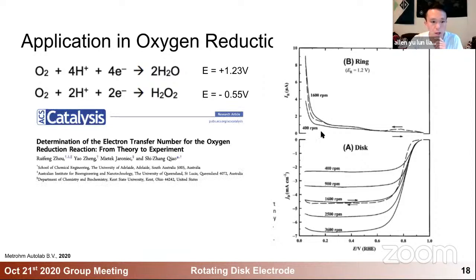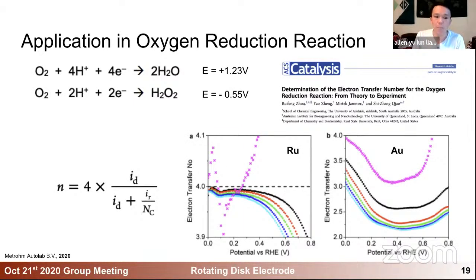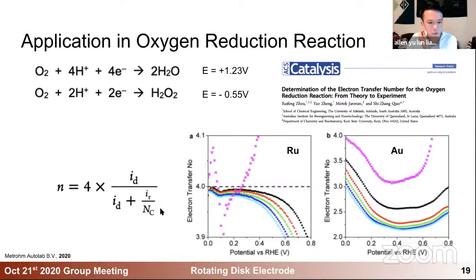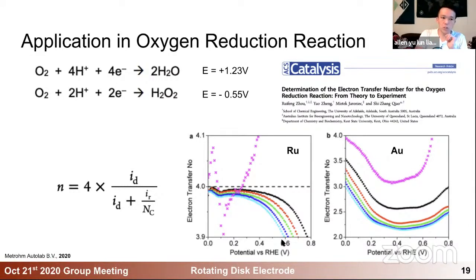And that has been applied in a lot of different literature, and this literature goes on to build a rigorous mathematical model on how you can actually back-calculate the average number of electrons transferred at this voltage for this catalysis on the disk. All you have to know, according to this paper, is the current at your disk, the current at your ring, and the collection efficiency for this RRDE setup, which is again mainly determined by the geometry of the RRDE electrode. And with this equation, they found that for ruthenium, it mostly stayed around 4-electron transfer between 0 to 0.6 volt versus RHE, meaning that ruthenium mostly just takes the oxygen and reduces it directly all the way to water. But for gold,